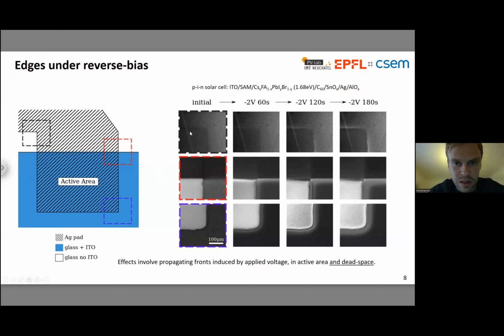So this region that I've colored in black is completely in the dead space. We're far away from the ITO electrode. We don't expect any charge injection of electrons and holes in this region of the device. And nonetheless, we see this activity occurring at the device boundaries. Okay, so both of these observations are fairly strong evidence that something involving ions might be going on. I mean, it's very hard to explain these features with any of the other mechanisms that I outlined briefly earlier.